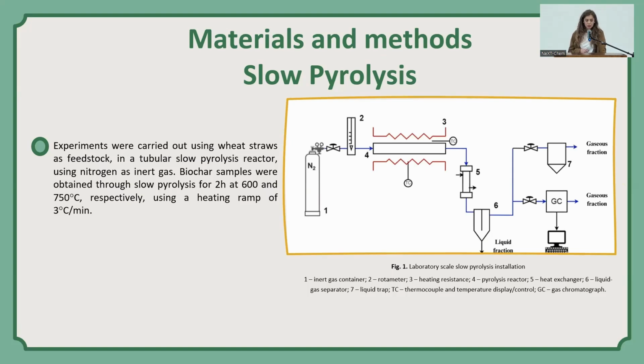After these 2 hours, the liquid and the gaseous phase was allowed to cool and separate in order to analyze both of these phases. And the biochar was also allowed to cool in the reactor, and after that was analyzed and activated.